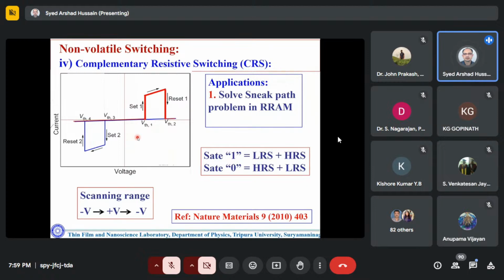But here, the 0 and 1 is not simply high resistance or low resistance. Rather, it's a combination of two resistance states. Because here, for example, say you are applying minus B to plus B. So we measure the resistance state of this region, negative polarity, then positive polarity. And if you go from this part to this part, plus B to minus B again, we measure the resistance state at the positive bias region and negative bias region. So 0 and 1 is a combination of resistance states at both positive bias and negative bias.